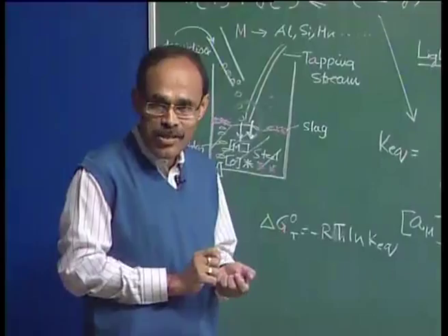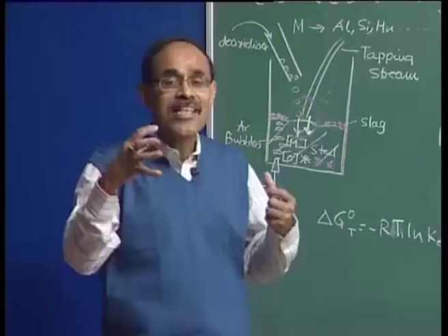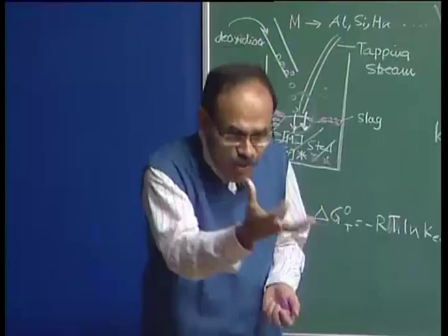There are other impurities also present in metal, but we are going to talk about them a little bit later. When we want to remove oxygen from the bath, we realize that we have to add an element which has a greater affinity towards oxygen. And we make sure that the oxidizing slag from the BOF, or the carryover slag, does not come to the ladle at all. Most commonly used deoxidizers are aluminum, silicon, ferrosilicon, ferromanganese, silicon manganese, etc.